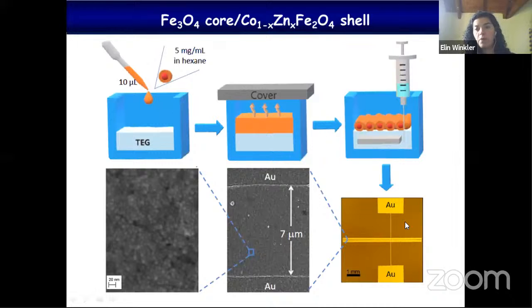And then, how do we deposit the nanoparticles on different substrates? Well, we use a liquid-air synthesis, where the nanoparticles are self-assembled, and a very uniform layer is formed at the interface between the liquid and the air, and then we remove the liquid and the nanoparticles are gently deposited on the substrate. This is the substrate where we have the two gold electrodes. This is a microscopy image. These are the gold, and here are deposited all the nanoparticles.